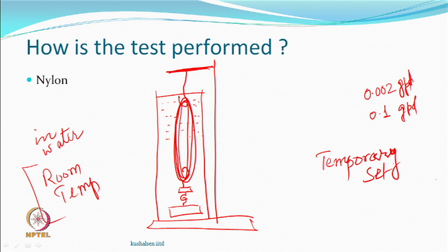Automatically it was not contracting, but it needed help. And it was obviously, when you put anything of nylon in water, the glass transition of this polymer goes down, and so the molecular mobility also starts, and suddenly you find that all the crimps which seemed to have been lost somewhere again come back. And so, this test was designed to be conducted in water, all right.